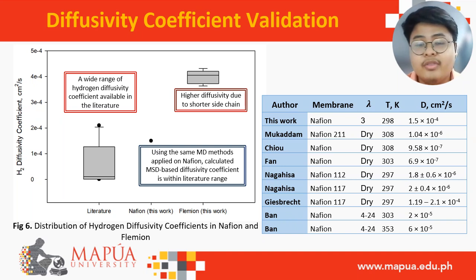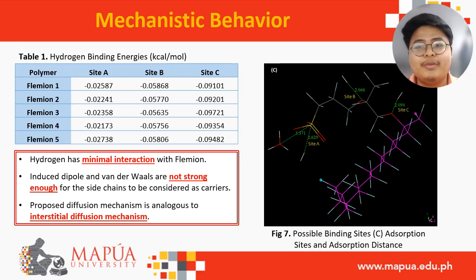Now, relative to the hydrogen diffusivity coefficients of Flemion, we have attributed this to the higher diffusivity due to it having shorter side chains. In order to determine the mechanistic behavior of hydrogen in Flemion, we calculated the adsorption energies as well as adsorption distances for hydrogen in Flemion, and we have determined that the possible adsorption sites for hydrogen in Flemion are all near the sulfonate groups as well as the oxygen groups, seen here in figure 7.